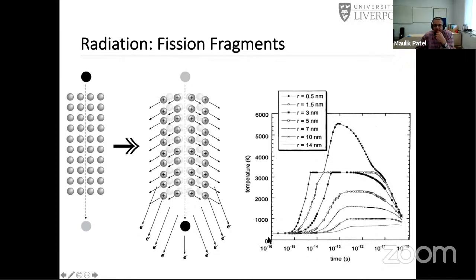And that leads to an enormous change in the temperature, about 4,000 to 5,000 degrees Kelvin, but in a few femtoseconds, not for a few seconds. Okay, so hence we call it the thermal spike. We get local melting sometimes, and then your structure changes.